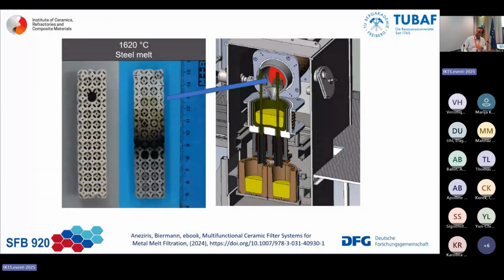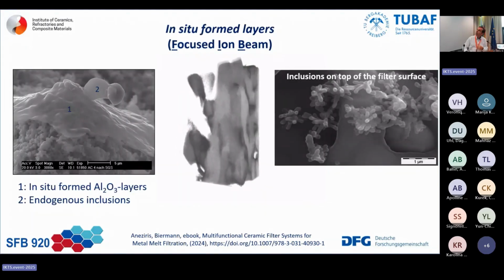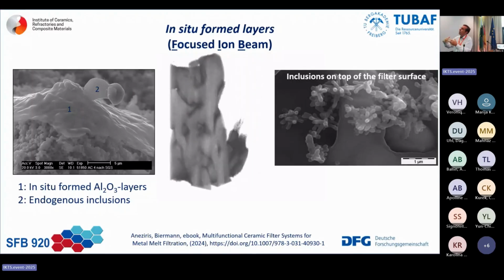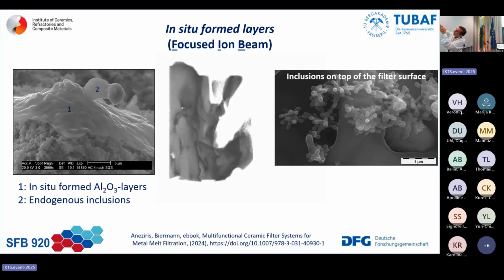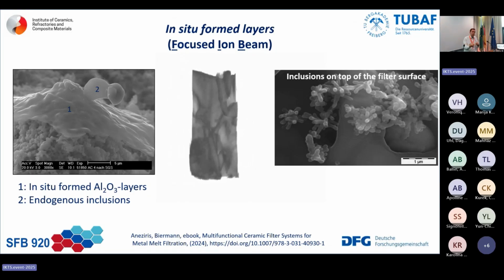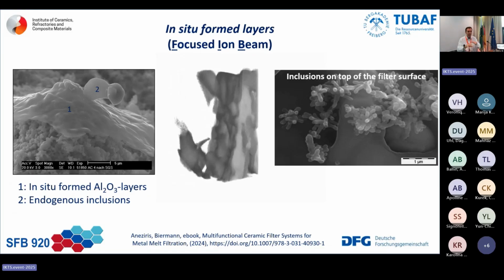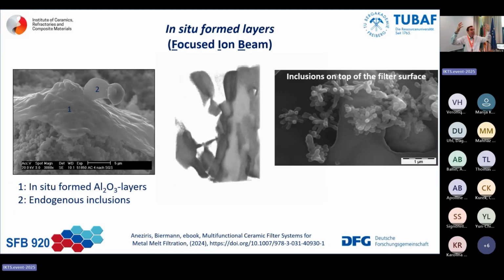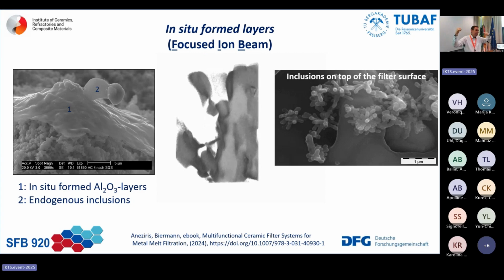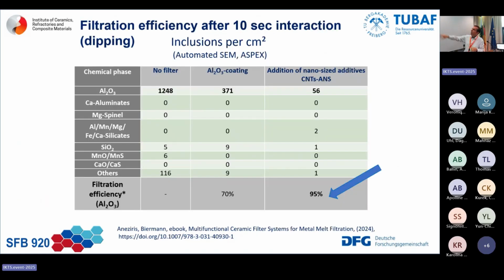And then you go to the steel casting simulator and you survive. And of course, you have to go today in situ with focused ion beam in order to be able to characterize much deeper this kind of layers that are created and are collecting the deposit. In this case, a positive. Emmanuel showed yesterday a bad deposit. Here is a good deposit because we pick up the ceramics out of the melt and we deposit on the ceramic. It's a very interesting issue because only this number, yes, you can filtrate up to 95% of the hard alumina inclusions in a steel melt.